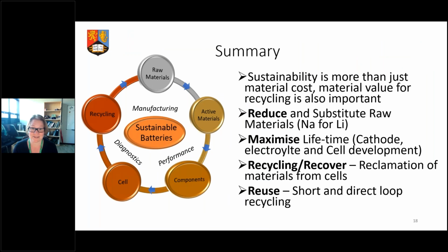So to just summarize, sustainability is more than just the material cost. The material value for recycling is important, as is the energy and the environmental input. What we need to do is reduce or substitute some of those raw materials, for example, sodium for lithium, nickel for cobalt, manganese for nickel. But also we need to look at the full life cycle of these materials, so maximize the lifetime of the cell itself, particularly for first life, but potentially we can maximize for a second life application as well. We also need to look at recycling and recovering those materials, and possibly designing in from the beginning ways that we can do this in a design for disassembly, and then looking at how we reuse those materials in direct loop or short loop recycling processes.